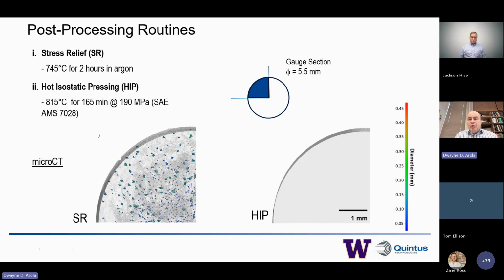But nonetheless, the important point is to compare that to what you see in the HIP condition. You can see that this is all gray. There's no evidence of pores within this microstructure. We were amazed when we saw this at first. We couldn't believe it. And then I'll show you the other evidence that comes from looking at the fracture surfaces. So I won't be showing any more micro CT results, because on the right-hand side there's nothing really to take a look at that gives us an indication of what's contributing to the performance of the metal.